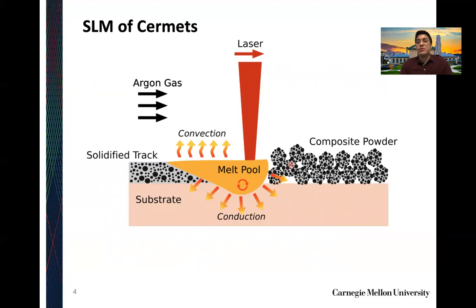If you look at this diagram here, you do have a composite powder lying on top of a substrate. Now, whether that's the build platform, the first couple layers, or essentially the pre-built part or the previous layers, what have you. So you have a laser that comes down, it melts your composite powder, and you get a liquid melt pool, which in itself has a lot of heat transfer effects going on: conduction from the melt pool to the composite powder, to the substrate, to the solidified track behind it; advection, or the flow of the liquid within the melt pool itself. You also have convection, heat transfer from the liquid melt pool into the argon gas, which is actually flowing across the top surface of the powder bed.